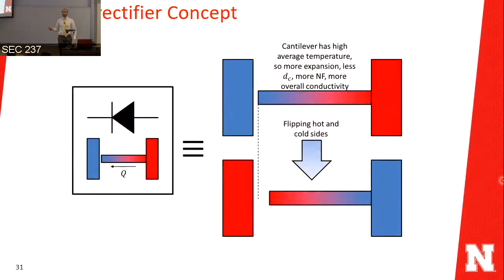So in our research, we are proposing a very simple idea, which is to have two terminals and a structure that can be expanded with heat. It's very similar to the structures used for the memory. And as you see here, if the side that's connected to the structure is kept at higher temperature, this gap will be smaller than in the other case when you flip temperatures. So you're expecting this to have higher heat transfer than the other case.